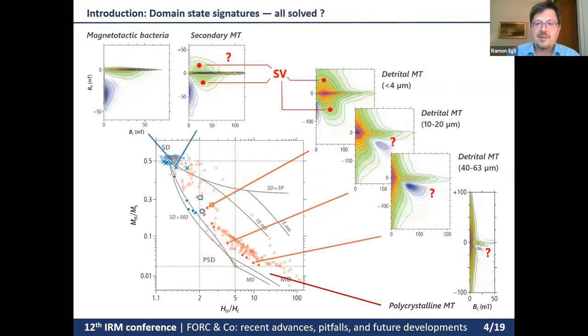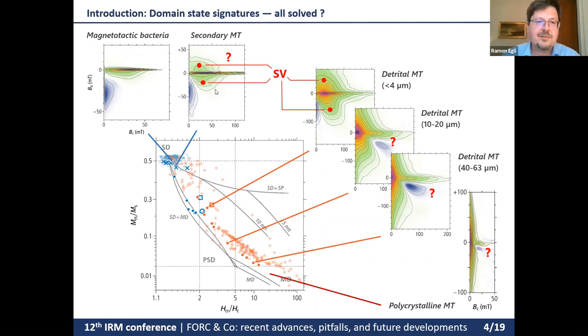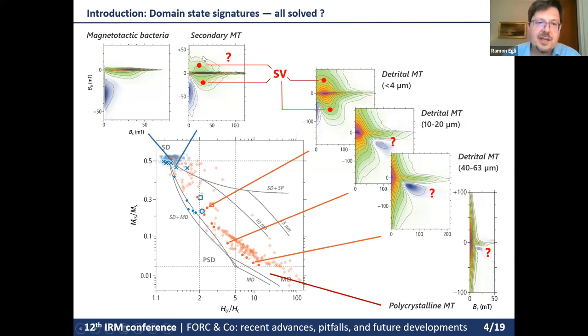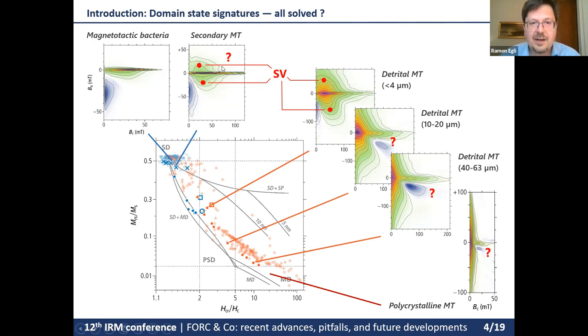Here is a summary of this new picture. But I want to draw your attention to some apparent contradictions. For instance, the secondary magnetite particles have a maximum size of about 100 nanometers, so they are predominantly single domain. However, we see these two lobes above and below the central ridge which resemble those of single vortex particles. So the question is: are magnetofossils associated also with single vortex particles, or what is the true origin of this signature around the central ridge?